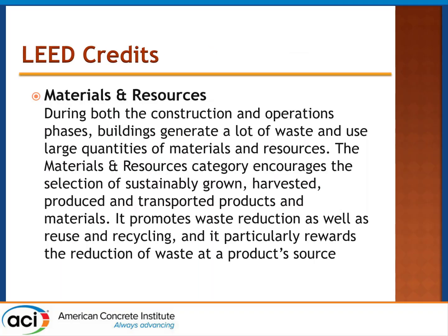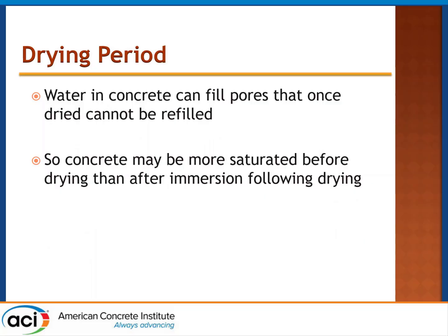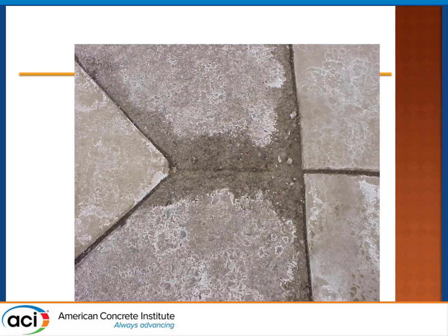We need to try to recover all of these materials, and this is an older slide, that's why it says LEED credits, because that's how we used to think about this. It's not how. But no matter what you make your concrete out of, it needs to cure and it needs to dry. This is an exposed concrete that used to be at the entrance to the headquarters of the ready-mix company that I worked for, undergoing a little bit of attack at the joints. So I used to refer to the parking lot as a museum of defects because it was paved with loads rejected from somewhere else.